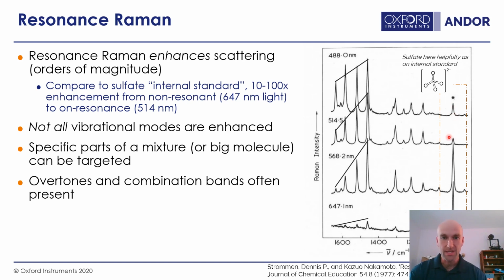And you can see that as we go onto resonance, our scattering is enhanced by a factor of somewhere around 100. It's hard to exactly quantify, and I just wanted to give a hand-wavy number there. But a factor of 100 is nothing to sneeze at. So we're getting quite a bit more in terms of practically just getting more signal out. And who doesn't like more signal?